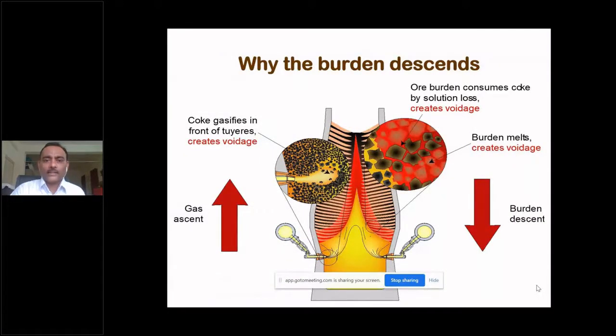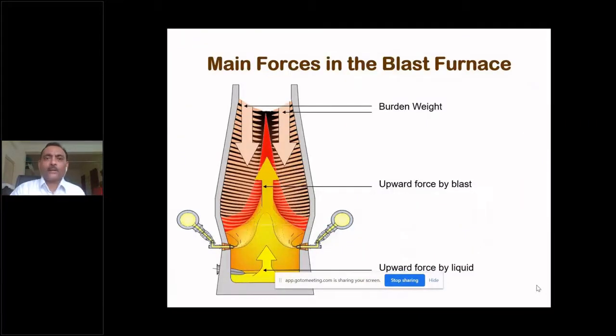The coke is the only thing which is looking black, through which the permeability happens. The gases go upward, and these black layers are layers of coke, so the reddish layer is a layer of iron bearing material like sinter, iron ore, and some amount of flux. This is the burden. Burden means the calculated amount of raw materials which we charge inside the furnace.